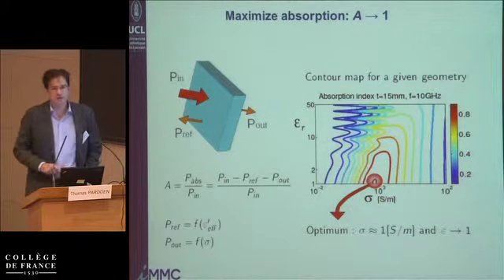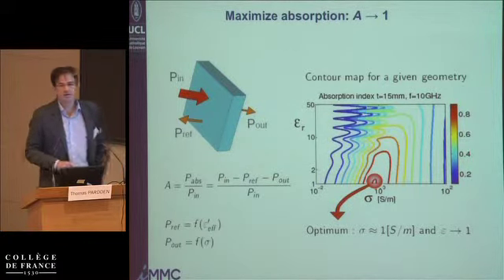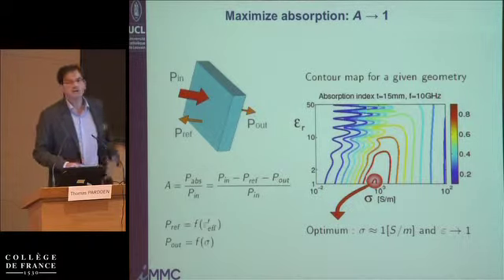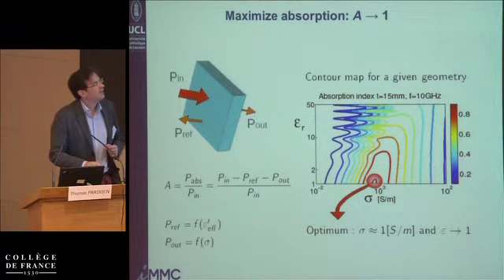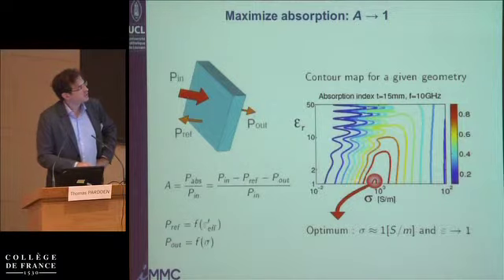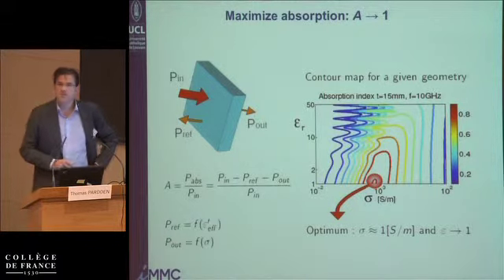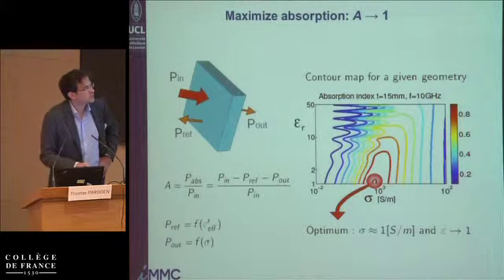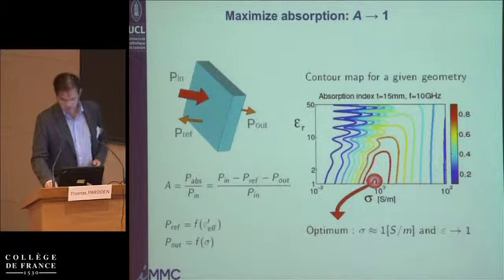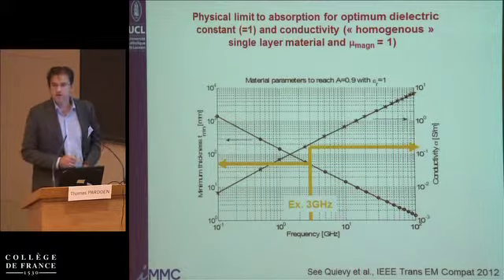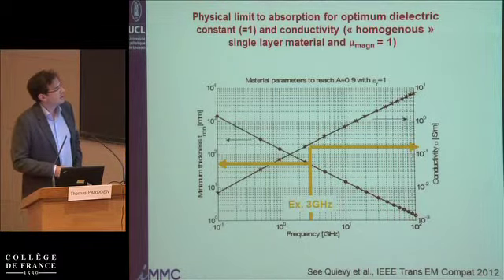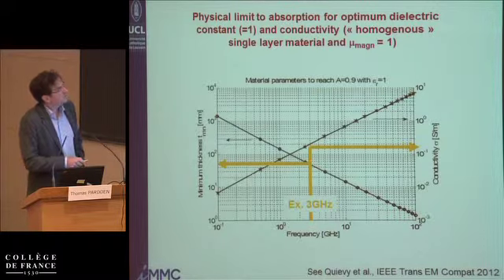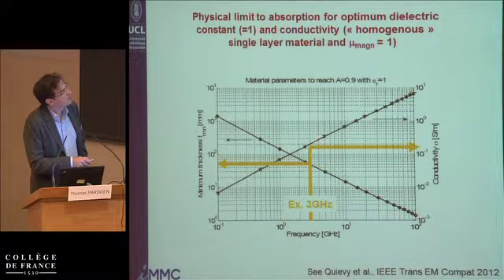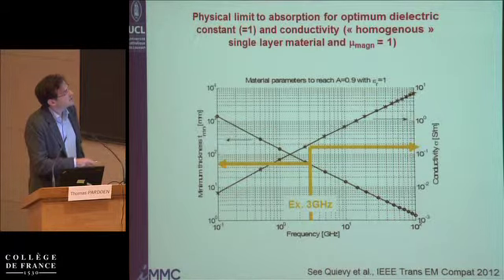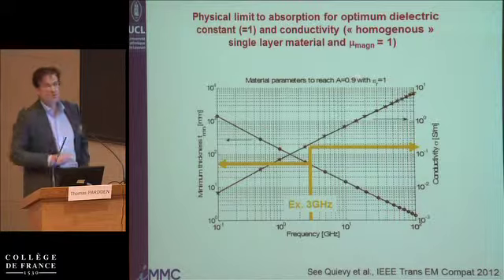Now, if you change the thickness, you will just change the magnitude of the absorption. So if you increase the thickness, you will just get more red here. And if you change the frequency, you're going to shift left or right the optimum conductivity, but not that much, just by a decade or two, not more than that if you change many decades in the frequency range. This is a plot where you see for a given frequency what is the optimum conductivity depending on the frequency, and what is the thickness that gives you the absorption index you want to reach.